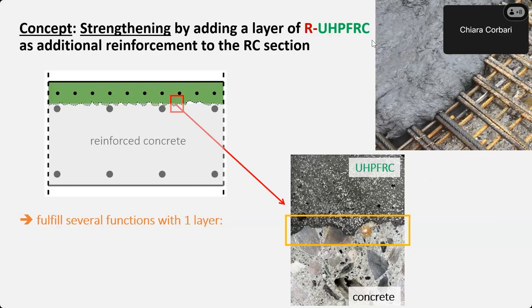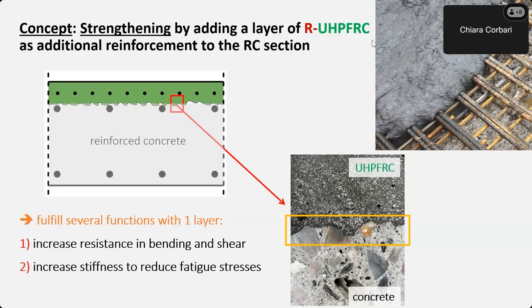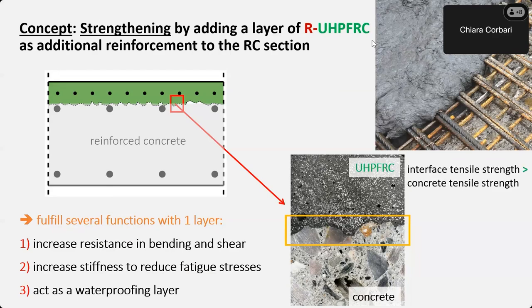We combine reinforced concrete and UHPFRC. The objective is to fulfill several functions with just one layer. Increase the resistance in bending and shear, increase stiffness to reduce fatigue stresses, because these are always the questions we have with reinforced concrete structures from the 1960s, 70s, and so on, and also act as a waterproofing layer. These are mostly the functions we need to fulfill. Now, if appropriate measures are taken, we get the perfect bond here. When you pull on such a composite situation, it will crack in the concrete.